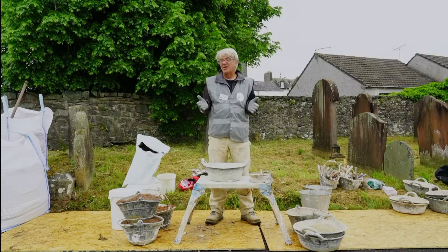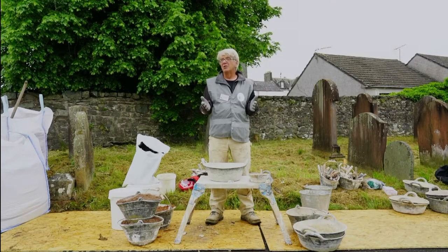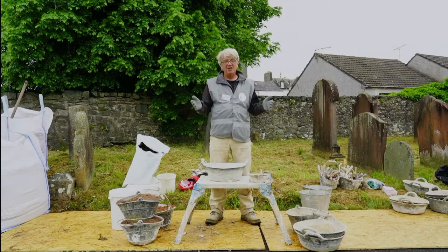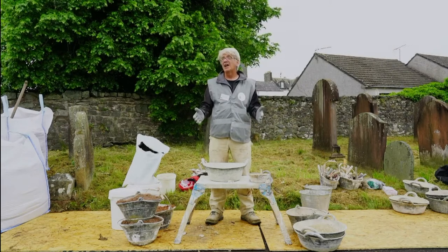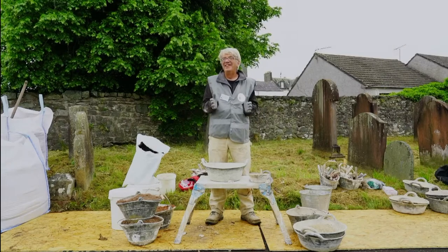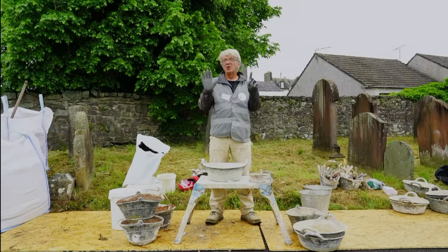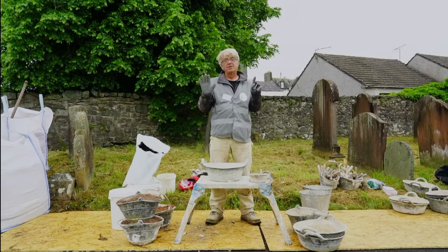But that was identified as being an utterly inappropriate sand for making mortars with, as long ago as 1780 by a guy called Bryan Higgins, an Irishman who did a lot of analysis in London at that time. And it's still the British standard sand, for goodness sake. So we've got one cement to five sand. That's the standard building mortar today. It's not workable, and it doesn't form a durable bond. It doesn't form a proper bond.